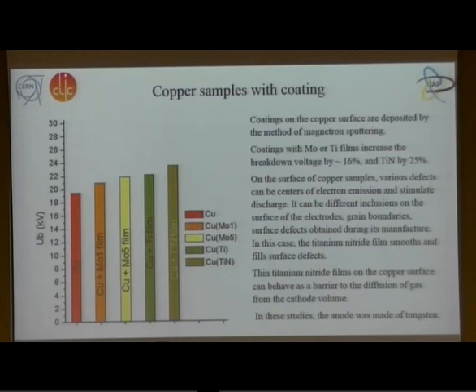These can be different inclusions on the surface of the electrodes, grain boundaries, and surface defects obtained during manufacture. In this case, the titanium nitride film smooths and fills surface defects. Thin titanium nitride films on the copper surface can behave as a barrier to the diffusion of gas from the cathode volume. In the study, the anode was made of tungsten.